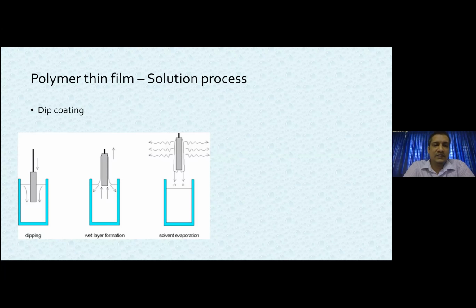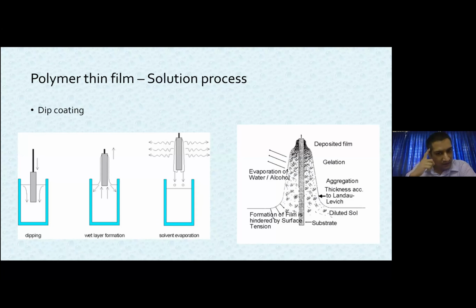So considering this, you can make a thin film coating. It depends on the nature of the polymer. One of the simplest approaches is something called dip coating, where you hang the substrate that is to be coated inside a container having a solution, and there is a rate at which you pull the substrate away from the solution. Due to that pulling off, you allow the solvent to evaporate, and then a thin film of this polymer is coated.